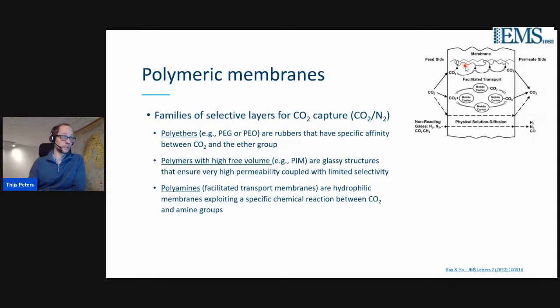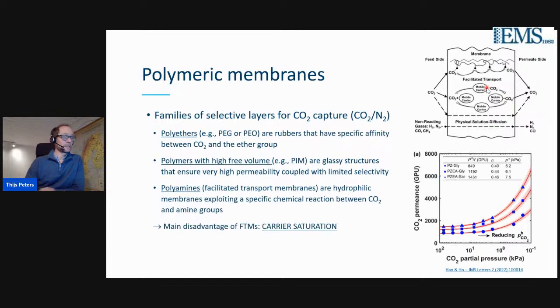And then the amine groups can either be fixed inside the polymer matrix, or the membrane material itself can contain a mobile carrier that reacts with the CO2 and transports it through the membrane. The disadvantage of these facilitated transport membranes is carrier saturation that normally happens at a very high CO2 partial pressure. Basically, the capacity of the mobile carriers or the amine groups that are present within the membrane is completely saturated with CO2, and even higher CO2 partial pressure on the feed side will not enhance the CO2 flux even more.